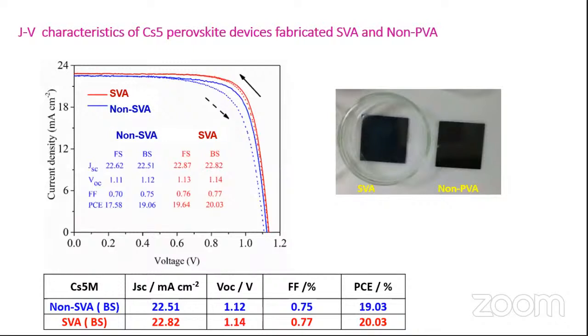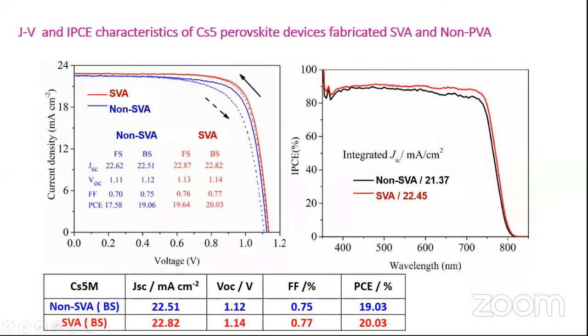Next we can see the photovoltaic characteristics of the devices fabricated by SVA and non-SVA methods. This is the JV curve. Here you can see the red one is the SVA annealed device, and the blue one is the non-SVA device. The SVA annealed one shows higher efficiency compared with the non-SVA method. The improvement of efficiency is because of the difference in the JSC. The JSC is higher in SVA due to larger crystallinity, which reduces recombination in the grain boundaries.